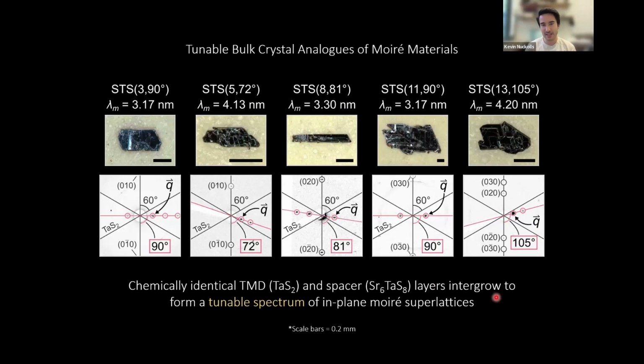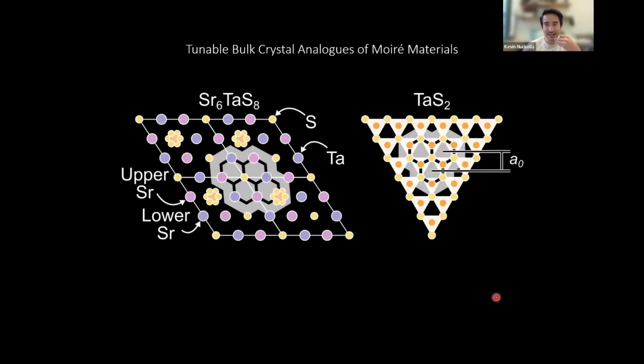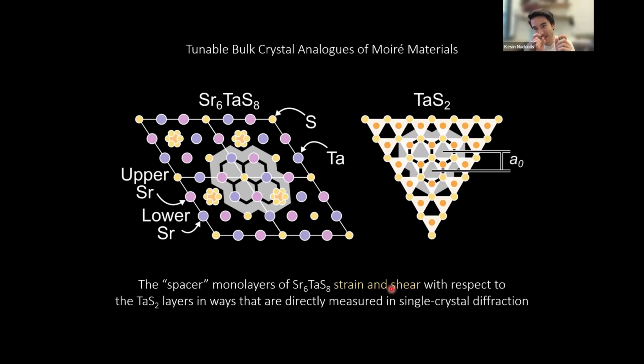At first, when we kept discovering these in crystal synthesis, it was very perplexing because I'm not using a transfer station to produce any of these Moiré superlattices. So what gives? How could I be stabilizing so many different compounds, but they're all chemically identical? So the key comes from X-ray diffraction, and it tells us that this tantalum disulfide layer in X-ray diffraction is very rigid. It basically occurs with the same lattice parameters every time. But this monoclinic layer can strain and shear in minute ways because the Moiré superlattice is an interference effect, that minute changes of the lattice constants of this guy produce very big distinctive signatures on the Moiré superlattice, very different Moiré superlattices that are again directly read out through X-ray diffraction.